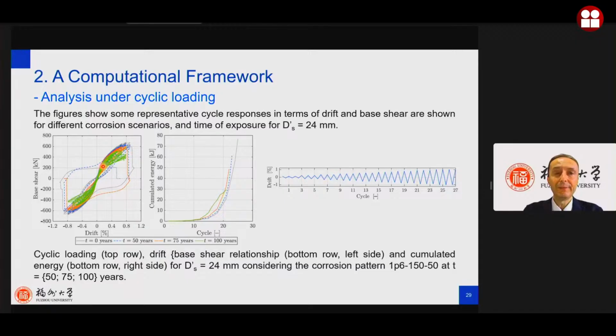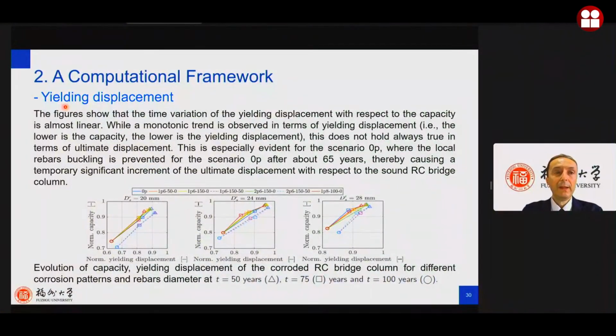What you obtain is that due to the aging and to the corrosion, the ductility of the cross-section is reduced. You can see, for example, at the beginning, the ductility is quite good, but after, with the green curve, that is this one, you can see that the hysteretic curve is influenced a lot. And we also find some link between the yielding displacement, considered after 50, 75, 100 years, and the bearing capacity. It seems there is a linear correlation.